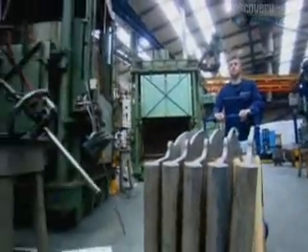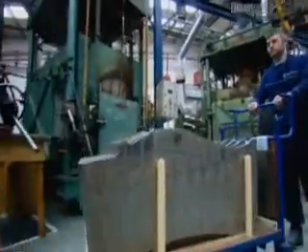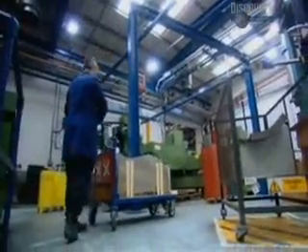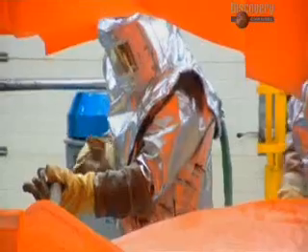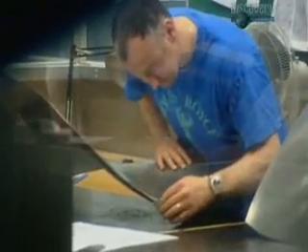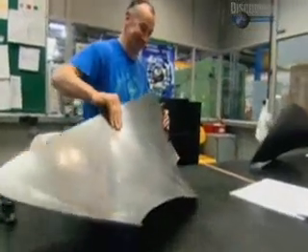Spinning at 3,000 revolutions per minute, the blades experience a force of more than 7,000 times their own weight, so everything is done to make them as light and as strong as possible. A top-secret process moulds the blades from ultra-strong, ultra-light titanium alloy. To save further weight, the blades are heated to 900 degrees in a furnace until softened, then gas is pumped into cavities inside, inflating each blade like a long, thin balloon. The result is a hollow part, curved in three directions for aerodynamic efficiency — supremely strong, yet light enough for someone to pick up easily. Each one costs the same as a luxury car.